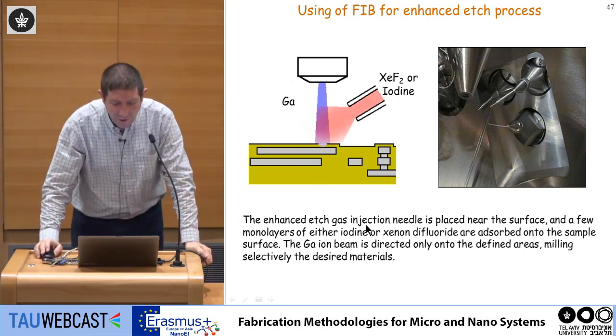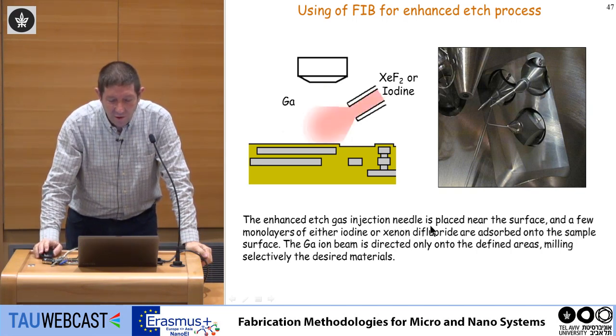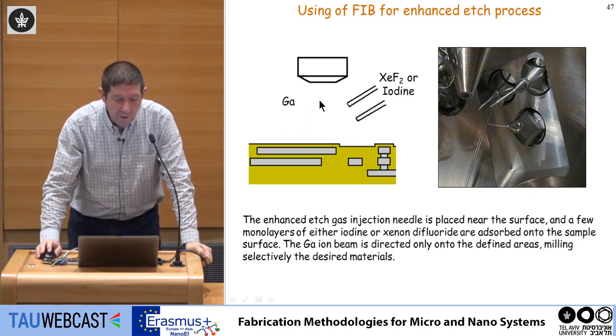So for the enhanced etch rate, a gas injection needle is placed near the surface, and a few monolayers of either iodine or xenon fluoride are adsorbed on the surface, and the gallium ion beam is directed only onto the defined areas, milling selectively the desired material. So you can do either gallium.